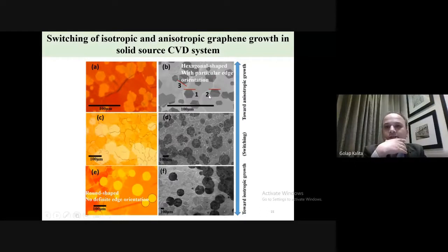So what will happen, let's say this domain and this domain have almost similar orientation, but this domain has a different orientation. Okay, so edge orientation is different. So these are the hexagonal crystals with different edge orientation. Then we get some kind of hexagonal or round shape, not perfectly hexagon, not perfectly round. Then in another growth process, what we get is a completely round shape. When you have a completely round shape, it is an isotropic growth model of the graphene domain. And when you have a hexagonal domain, you have anisotropic growth. Okay, edges are defined here; here, edges are not defined. It's a round shape.